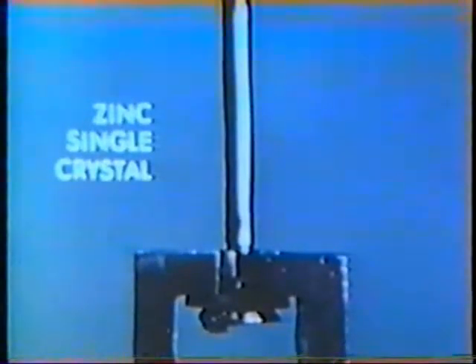The tensile specimen shown deforming is a zinc single crystal, which has a hexagonal close-packed crystal structure. This view is in the direction of slip. Note that the width does not decrease as the specimen elongates. If the deformation is observed from the side, the slip direction is in the plane of view and can be readily seen. Note that in this orientation, the width decreases as the specimen elongates.